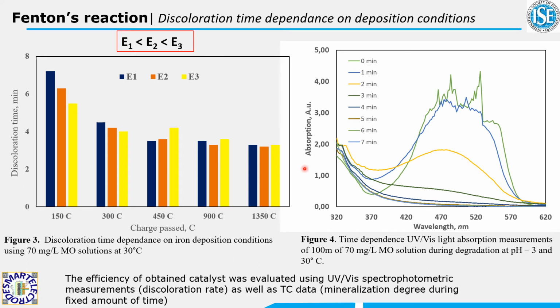We tested what effect iron deposition potential and deposition time, or charge passed, has on the solution's discoloration time. The discoloration was tracked using a UV-visible light spectrophotometer. Typical light absorption dependence was measured from 620 to 320 nanometers, trying to prevent UV illumination and in turn activation of hydrogen peroxide breakdown. The main peak is around 480 to 490 nanometers and is related to the chromophoric double nitrogen bond in methyl orange. Measurements were done every minute.